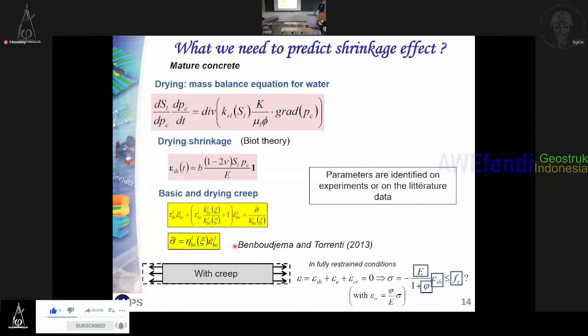And we also use creep models because, as an example, assume that you have complete restraint of the concrete due to shrinkage. If you have complete restraint, the total deformation is equal to 0. It's the elastic strain, plus the shrinkage strain, plus the creep strain. If you assume very basically that the creep strain is proportional to the stress, you will find that the stress is proportional to the Young modulus. So the more the Young modulus is important, the more the stress is important, along with the shrinkage, but also the creep. Creep is negative if you are looking at deflection or prestress loss, but regarding cracking risk by shrinkage, it's positive. In this simple calculation, if the stress is higher than the tensile strength, you may have cracking. So it's very important to have access to creep in order not to overestimate cracking.